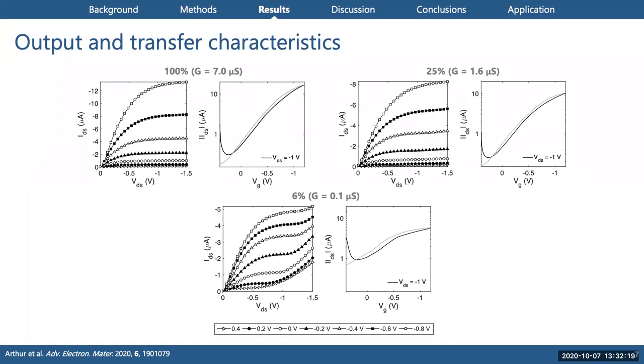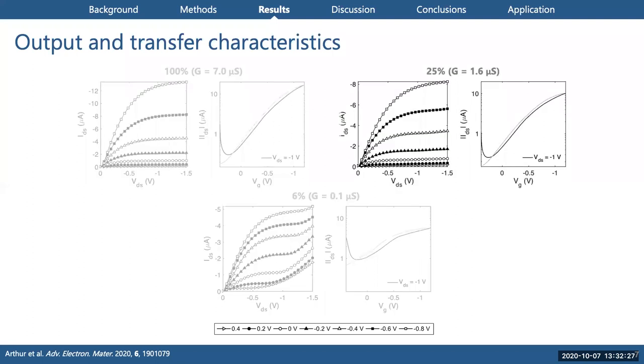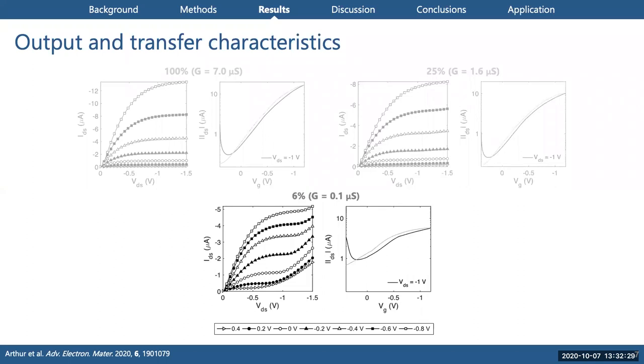The layers were spin-coated on top of a glass substrate patterned with ITO contacts, and we used drop-cast PEDOT:PSS as our model gate electrode. The electrical conductance, or inversely the resistance, of the gate was varied by diluting the PEDOT:PSS solution, and so this results in varied film thicknesses with the result being different PEDOT:PSS conductances.